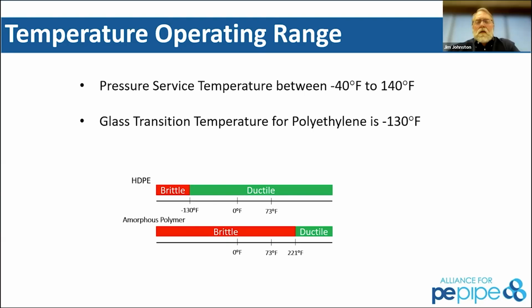So go ahead, Jim. The material itself, polyethylene itself, has a service temperature range from -40 degrees, which is roughly -40 degrees Celsius, to 140 degrees. That's your operating temperature for the material in process. You're going to have some applications where you're going to be hotter than that, but you're going to lower the pressure. The glass transition temperature, meaning when is this material going to fracture if I hit it, is minus 130 degrees Fahrenheit. Hopefully none of us ever have to see minus 130 degrees Fahrenheit. But that means it's much more flexible. It has much more capability.